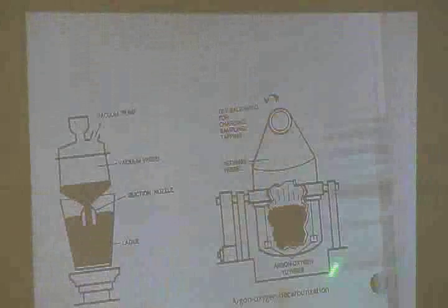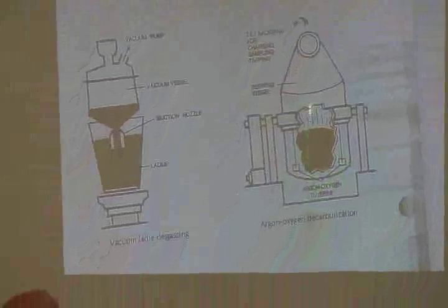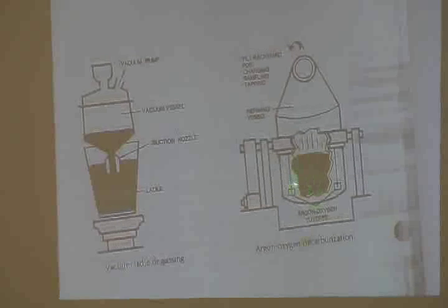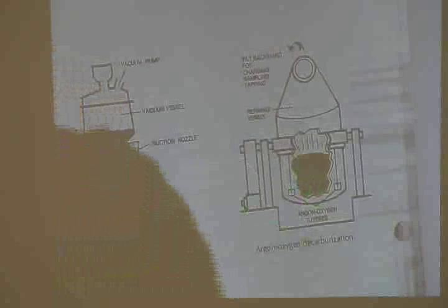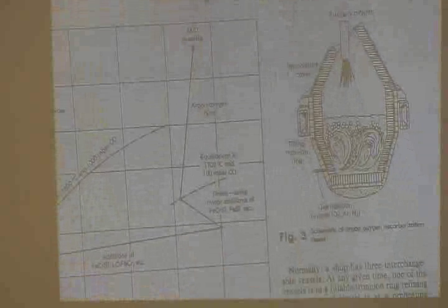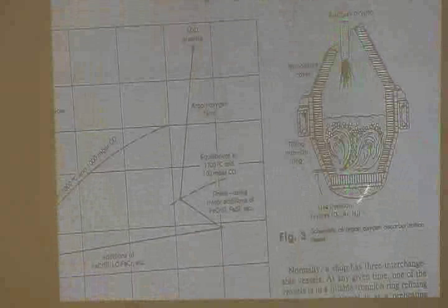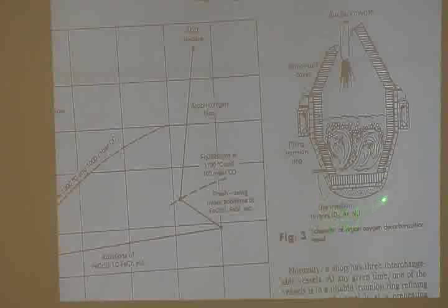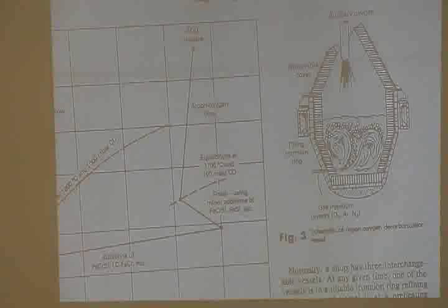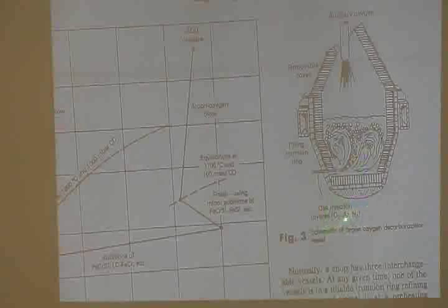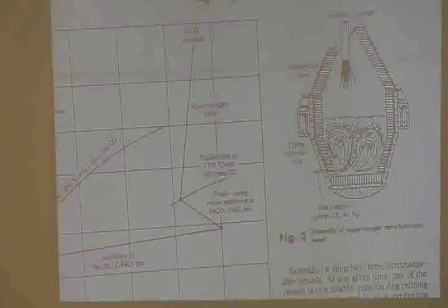Here's the picture of argon oxygen decarburization. So you have argon blown in here and just a big vessel to do that, and here's actually a better picture, you've got auxiliary oxygen to get the carbon down. You blow the oxygen. Nowadays we actually first blow with nitrogen. You can't blow with all nitrogen because then the nitrogen in your steel will go too high and that can create problems. But you start off with nitrogen, get most of the oxygen and carbon out, and then you finish off with argon. Argon's expensive, but so is stainless steel.